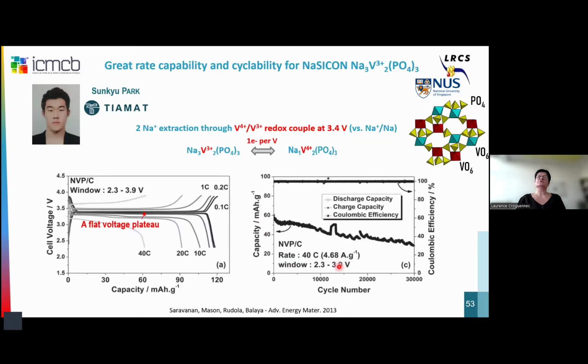So then I also wanted to highlight these results concerning these new NASICON materials that we recently published. This work was performed by Sunkyu Park in Tiamat, starting from very old materials. You know, these NASICON materials, Na3V2(PO4)3. In that material, you have vanadium 3 plus. And this material behaved very well. We have a flat plateau. We have the exchange of 2 sodium per formula unit and 1 electron per vanadium, so vanadium 3, vanadium 4. And you can see that we have very good performance at high rates.